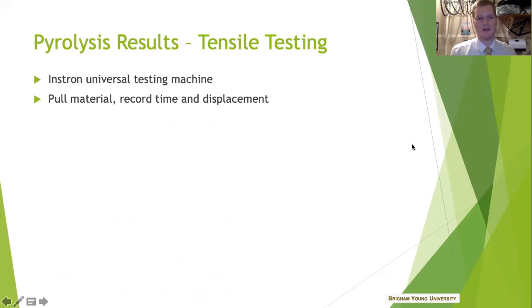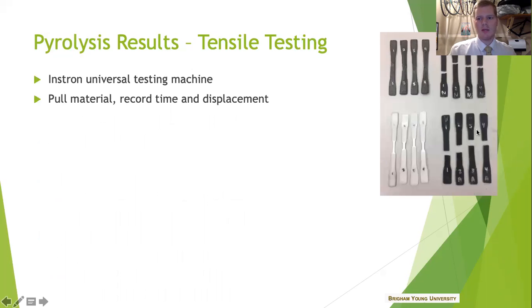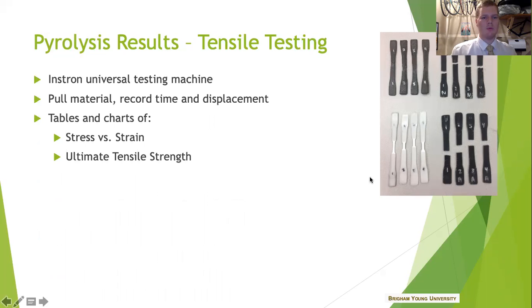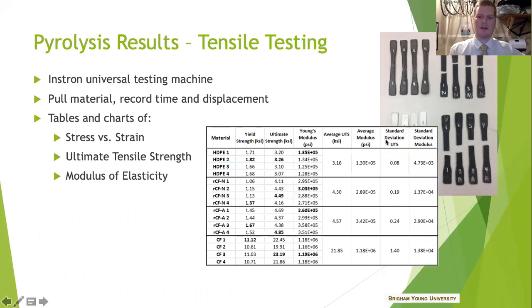Let me show you here my tensile testing results. After I got these images, I was really excited to see what the data would show. So here it is. With the Instron, I made a bunch of different samples, just some basic carbon fiber, 100% carbon, just to see. Here's my HDPE, and then as well, my recycled carbon fiber mixed with the HDPE. Both of these were 10% by weight fiber content. Some were, again, in nitrogen, and some were ambient. So I made sure to keep track of both of those and keep them nice and separate. So I pulled the material, got the data from that.